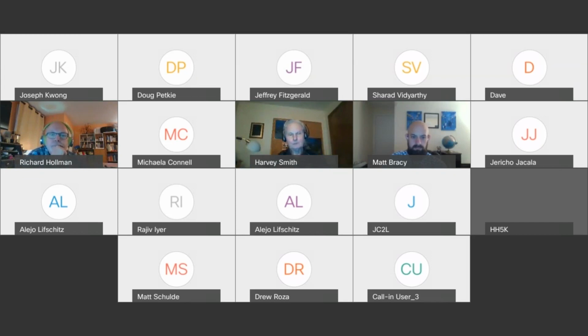Yeah, so we actually did some shear tests with both the unplasticized and plasticized dry films, and they had identical adhesion, at least by shear test, on copper, silicon, and EMC. In terms of the comparison to other polyimide dry films, I'm not sure, but at least compared to ours without the plasticizer, they were identical.